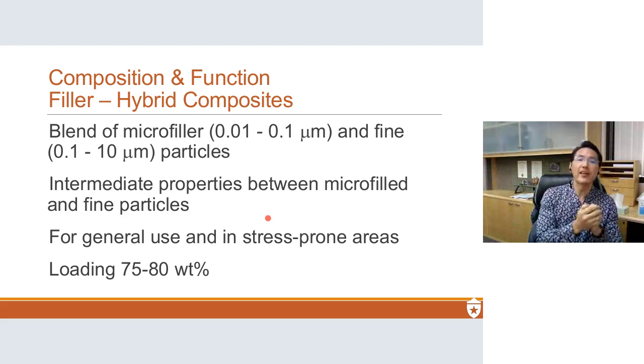The only problem is they're not as good as larger particles because these aggregates are not chemically bonded. And so if a fracture comes through, it kind of acts like a hole. So they're not as good as large filler particles. Did that help clarify? So when we look at a composite, very rarely will they tell you that they have clusters. 3M actually says that they have clusters, and they claim that their clusters are so tightly bound that they don't weaken mechanical properties. I don't know if they made a modification to their surface, but that's what they claim. I have not seen any other commercial brand that claims or admits to clusters.